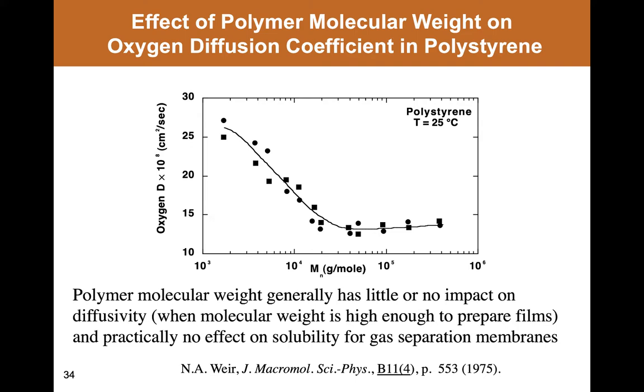So what's shown here is the oxygen diffusion coefficient in polystyrene as a function of the molecular weight of polystyrene, number average molecular weight. And what you can see is that the oxygen diffusion coefficient decreases some, less than a factor of two, and then essentially becomes independent of molecular weight.